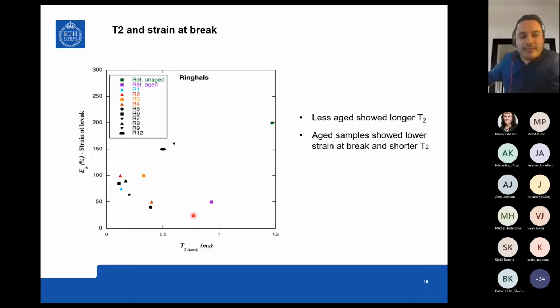So you actually can see that it's a rather big influence from the cable constructions and also these ferromagnetic components that can affect the NMR sensor compared to the more traditional polymer samples that exist. But when we look at the data more closely, we can clearly see that these two data points, R9 and R12, are essentially cables which are new. They haven't been aged. And if you put them into the context of these other samples which have been in use, we can see that there is a difference in relaxation time between the new and the used cables.